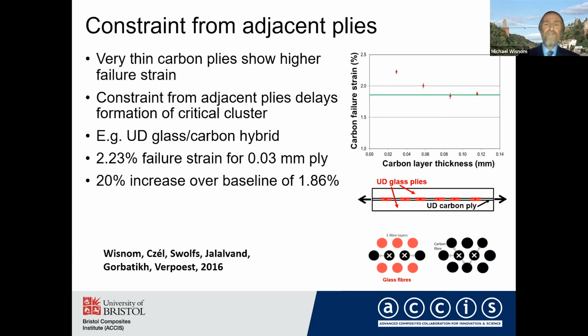So in the limit here, if you consider a specimen which has only got one layer of carbon fibers, when these carbon fibers break, then if these ones are glass, there are no fibers there for them to connect up with. So it's more difficult. They have to break these ones here. Whereas in a cluster of carbon fibers here, there's more fibers that they can link up with, and so it's easier to form a critical cluster. So in these thin plies, we have a constraint on that cluster formation, and hence we see an increase in